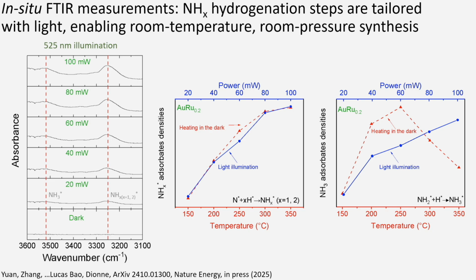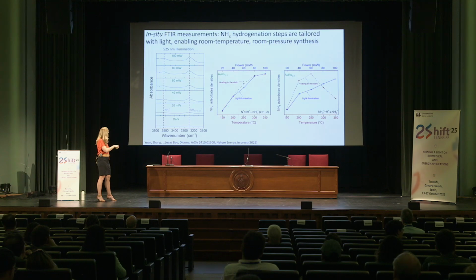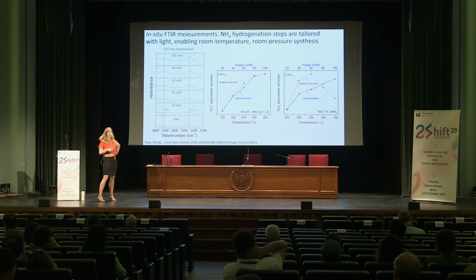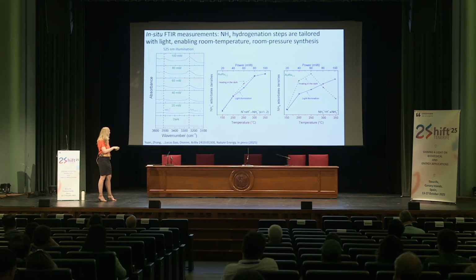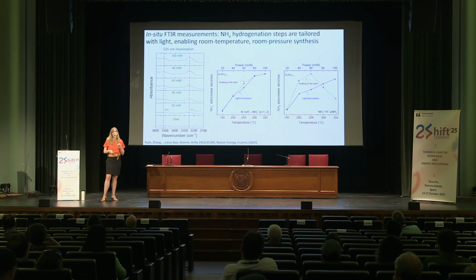And I'll just very briefly go through these intermediates where, for example, we're looking at the NHx adsorbate densities and also the NH3 adsorbate density. So here what we're doing is looking at different intermediates at different time scales during the reaction. And what you can see is for this particular intermediate, where x is either equal to 1 or 2, whether you're in the dark or with illumination, that intermediate isn't changing. But you can see here, when you're heating versus just using light illumination, this NH3 adsorbate density changes quite dramatically.